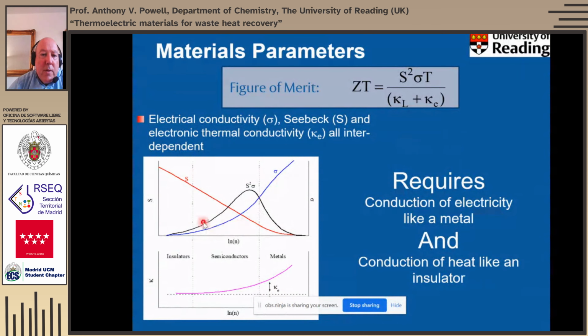So for instance, if we were to plot these parameters as a function of the charge carrier concentration along the x-axis, we'd find that the materials that have a very high value of the Seebeck coefficient are generally insulators or non-metallic materials with a fairly low charge carrier concentration. And of course, what that means is that they have a very low electrical conductivity. Conversely, if we go to materials which have a high electrical conductivity with a high charge carrier concentration, they've got a low Seebeck coefficient. So there's a trade-off in terms of the numerator of this expression.